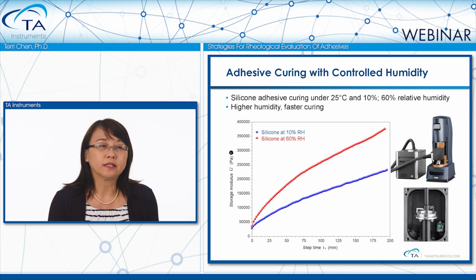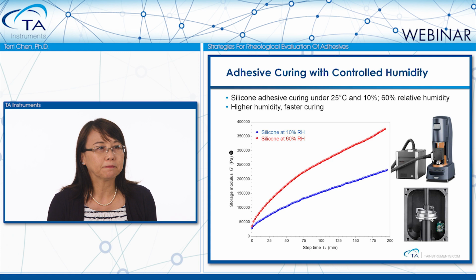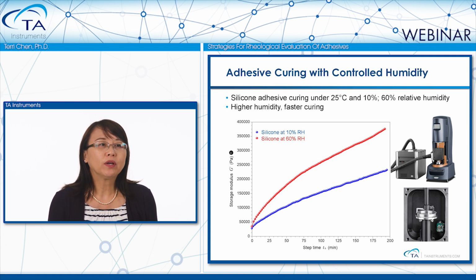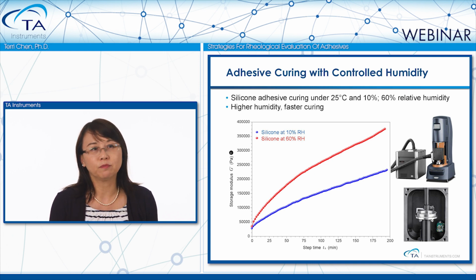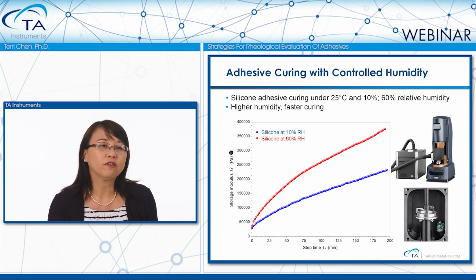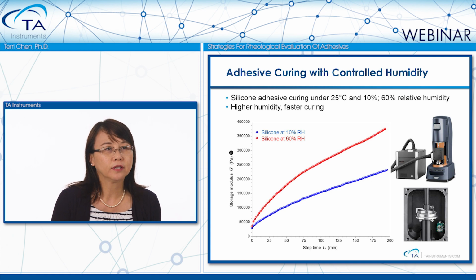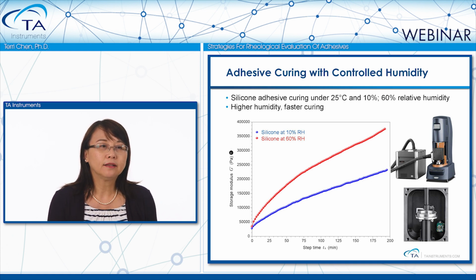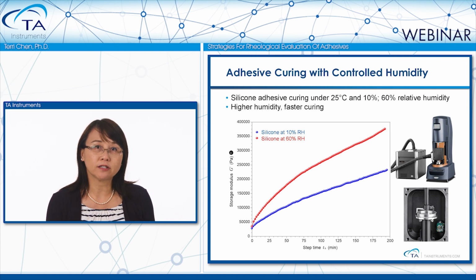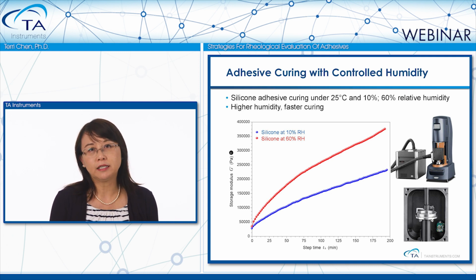The silicone-based adhesive curing is sensitive to the environmental humidity. Using a rheometer with a humidity control chamber, we can monitor the curing process with a controlled temperature and also humidity. This graph shows an example of monitoring a silicone caulk curing under different humidity levels. The results have shown that this sample cures much faster under a higher humidity environment.